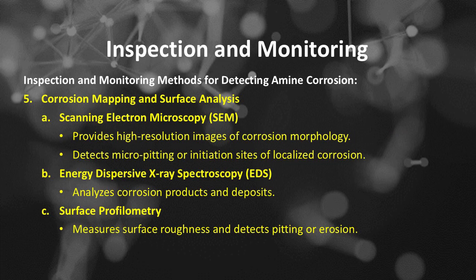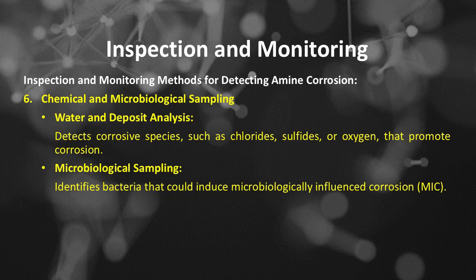Inspection and monitoring methods. Number 5 is corrosion mapping and surface analysis, which includes, number A, scanning electron microscopy, providing high-resolution images of corrosion morphology and detecting micropitting or initiation sites of localized corrosion. Number B, energy dispersive X-ray spectroscopy, analyzes corrosion products and deposits. Number C, surface profilometry, measures surface roughness and detects pitting or erosion. Number 6 is chemical and microbiological sampling, which includes water and deposit analysis, detecting corrosive species such as chlorides, sulfides, or oxygen that promote corrosion. Microbiological sampling identifies bacteria that could induce microbiologically influenced corrosion, MIC.